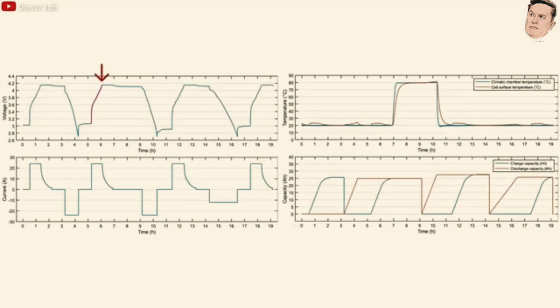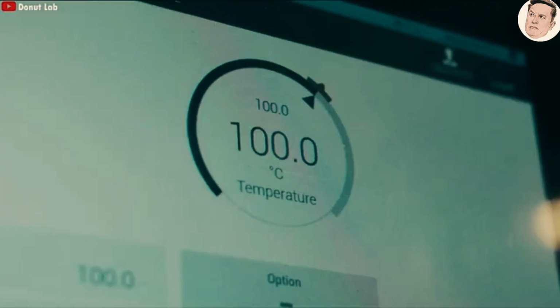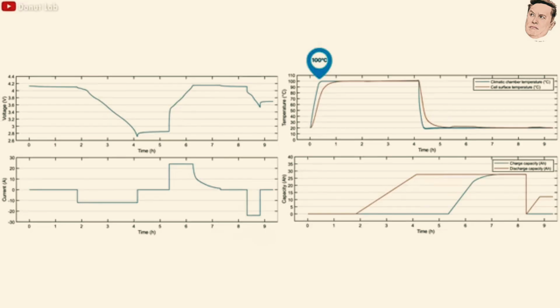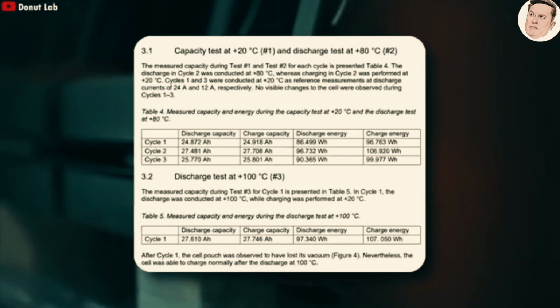After the battery was fully charged using the standard procedure, the temperature inside the test chamber was raised to 80 degrees Celsius and held there for 2 hours. At this temperature, the battery was discharged at the same 24 amp rate and delivered 27.5 amp-hours, reaching 110.5% of its room temperature capacity and exceeding the 24.9 amp-hours measured at 20 degrees Celsius. Finally, at a temperature of 100 degrees Celsius using a discharge rate of 12 amps, the battery delivered 27.61 amp-hours, corresponding to 107.1% of the reference capacity at the same discharge current.